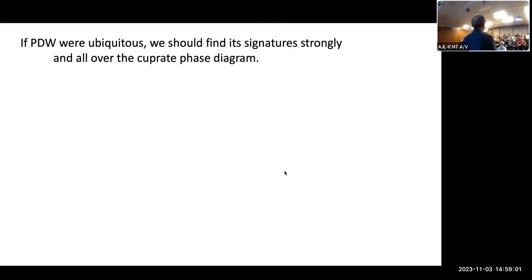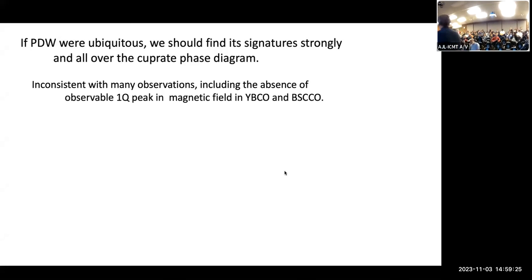Now I'm going to come to Duncan's question. So here I looked in one special cuprate which shows this layer decoupling, which is a spectacular but rather special set of phenomena. Most cuprates don't exhibit layer decoupling. Do we think that they nonetheless have a pair density wave? So there's a way to look for that. We know that we can see these charge density wave orders, which I'm going to call a 2Q peak for the reasons we discussed. That's the charge density wave.